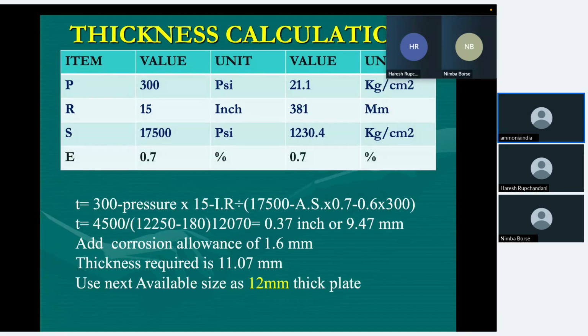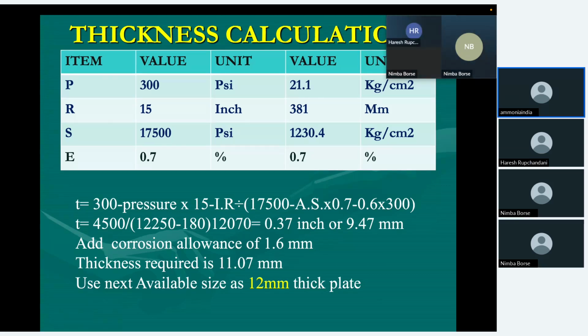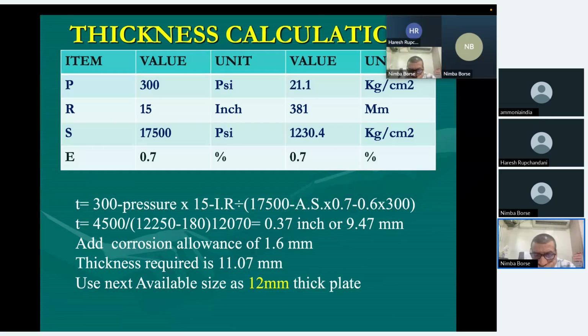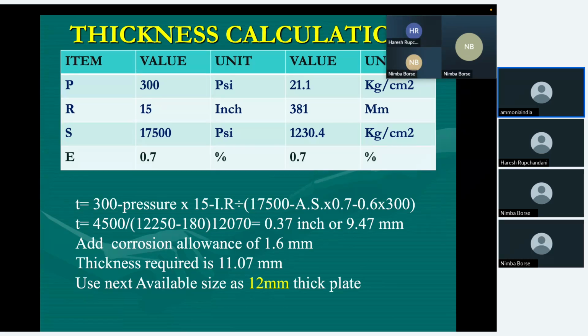I have just given this calculation: pressure 300 psi, which is 21 kg per square centimeter, internal radius 15 inch, allowable stress 17,500 psi, and let us assume joint efficiency 0.7. We are not carrying out any radiography. So the thickness will be 300 psi into 15 internal radius divided by 17,500, that is allowable stress, into 0.7 minus 0.6 into the pressure, as per the formula given on the earlier page. So the calculated thickness is 0.37 inch or 9.4 millimeter. Add corrosion allowance 1.6. So the required thickness becomes 11.07 millimeter.